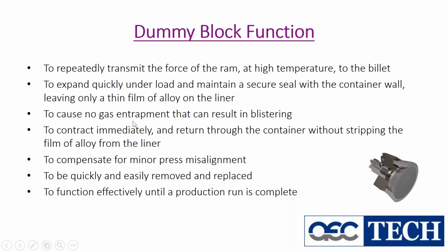The dummy block's function: to repeatedly transmit the force of the ram at high temperature to the billet. Simple. Expand quickly under load and maintain a secure seal with the container while leaving only a thin film of alloy in the liner. Now, I'm going to cover that a little bit more in the next few slides. To cause no gas entrapment that can result in any blistering, and to contract immediately at the end of the cycle, so that way when it pulls back through the container, you're not pulling any of that precious aluminum skin out of the liner.